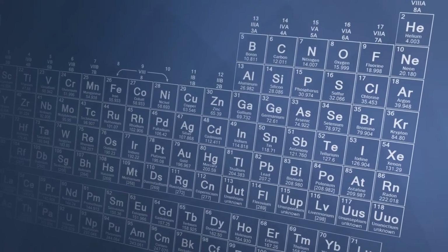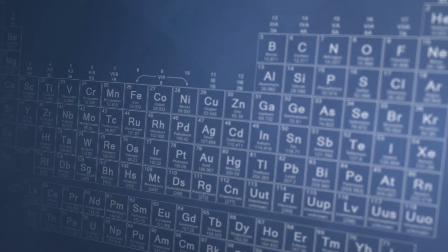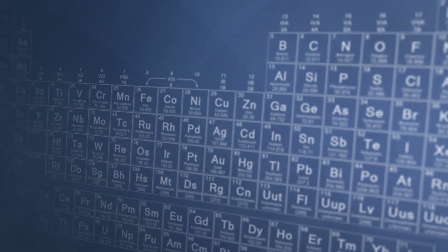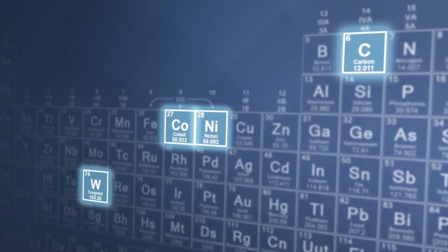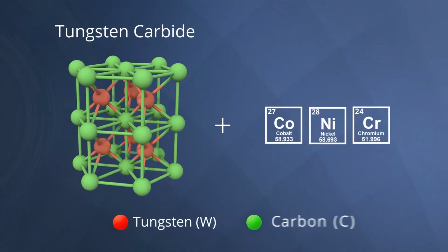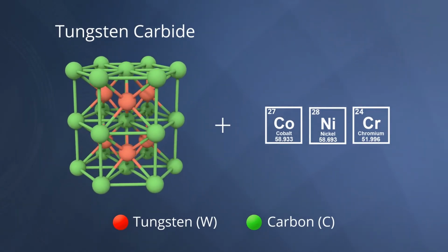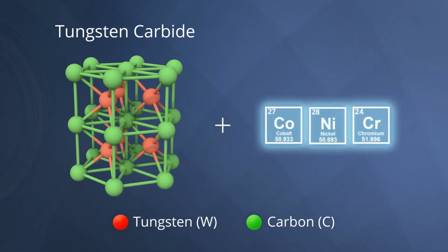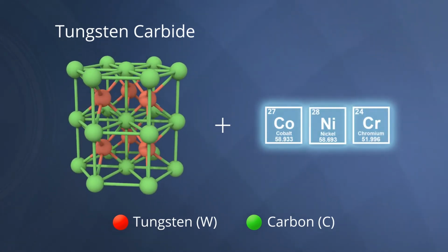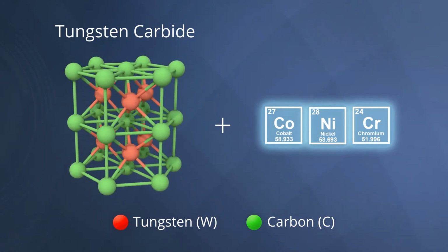Now let's discuss the role of trim material in resisting erosion. For a long time, choke manufacturers selected their trim material from a nickel or cobalt binder tungsten carbide. To address both corrosion and erosion, carbide vendors began using a composite binder, a mix of cobalt, nickel, and chromium in a tungsten carbide matrix. This material is traditionally referred to as tungsten carbide.